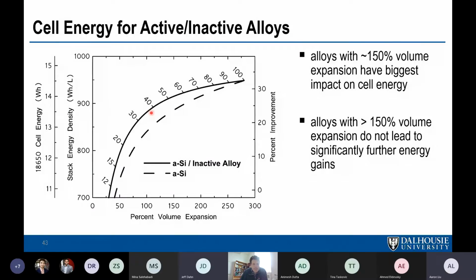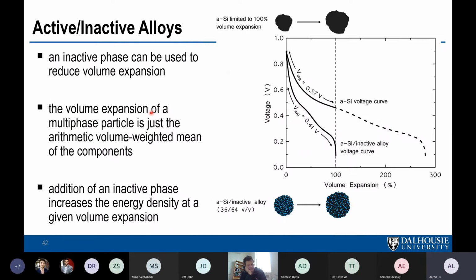So you mentioned earlier that as you have more inactive phase, then you can go lower when you're lithiating. So if you use, say, graphite as the inactive alloy, and you don't have too much silicon, can you access the graphite capacity that way? Earlier, a couple of slides ago, on this slide, you were saying that as you have less silicon and there's more inactive, to reach the 100% volume expansion, you can go lower in voltage to use more of the silicon, right?